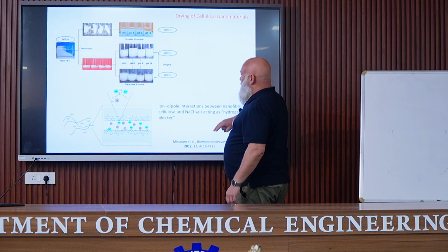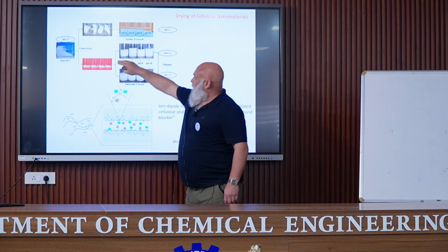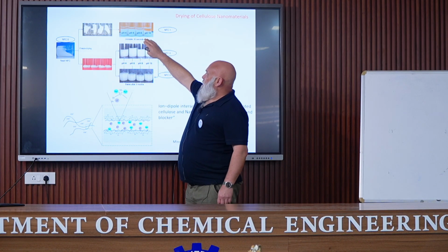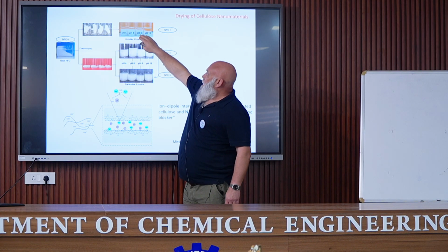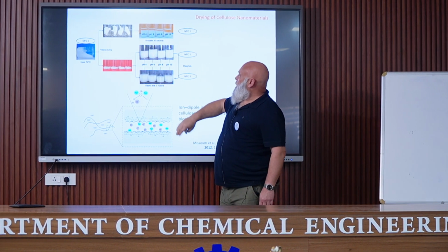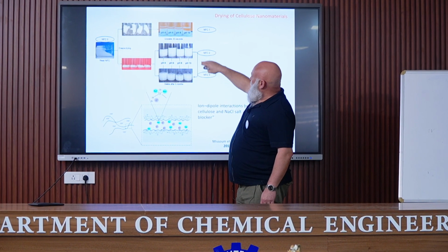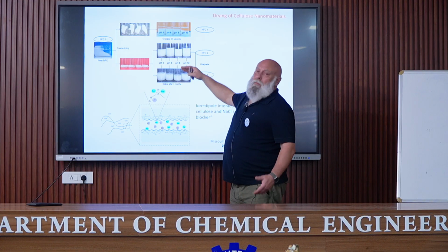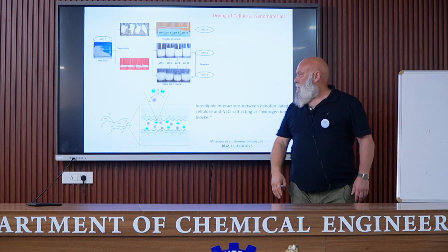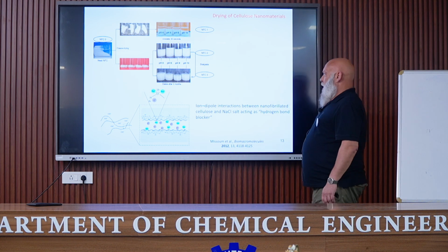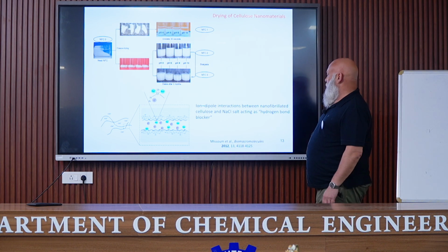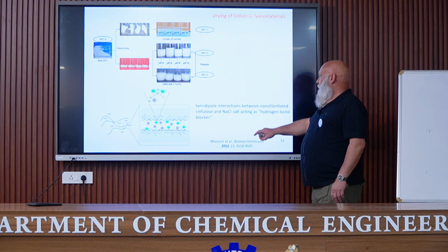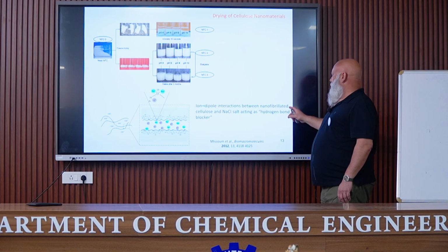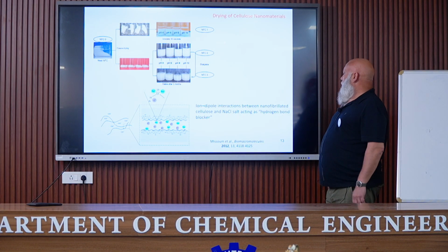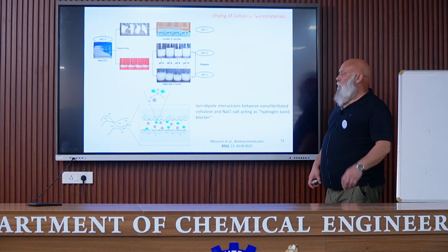So I will not maybe go too into the detail, but when the CNF were dried and then redispersed in water, we observe this sedimentation for different pH. And when adding salt, so I don't remember exactly the difference between these two, we can see that the sedimentation is limited. And this is because of the insertion of the Na+ and Cl- ions. We have ion-dipole interaction between the nanofibrillated cellulose and NaCl salt, which acts as a hydrogen bond blocker.